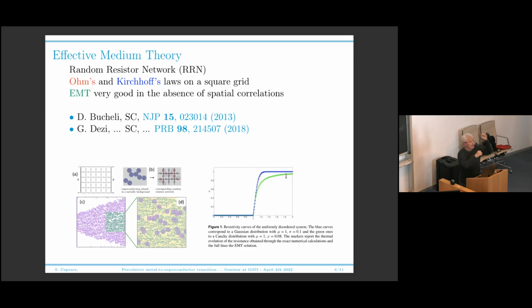So you assign a zero resistance or a finite resistance completely at random in your system. In this case, the effective medium theory gives a very good solution. The blue curve is a Gaussian distribution. The green curve is a Cauchy distribution, or a Lorentz, if you wish, distribution, which is much broader, with much fatter tails. But you have a very nice solution with the effective medium theory for the Gaussian distribution, for the Cauchy distribution.